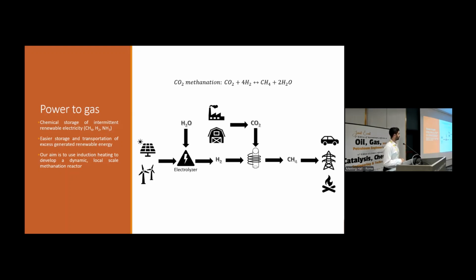such as CH4. So by doing, for example, this reaction, the methanation, CO2 methanation reaction. And our aim is to develop an induction heated methanation reactor, which will be used in order to do the reaction, and to have a reactor that is dynamic, local scale. First of all, dynamic because the energy source is intermittent, local scale, and of course, good energy efficiency, and that can produce cheap CH4.